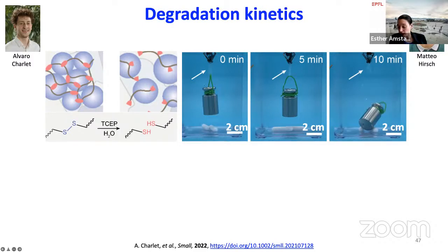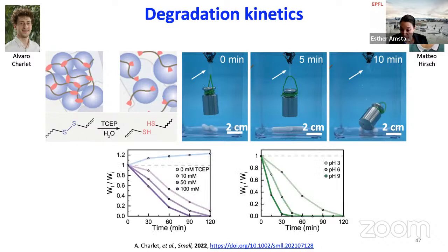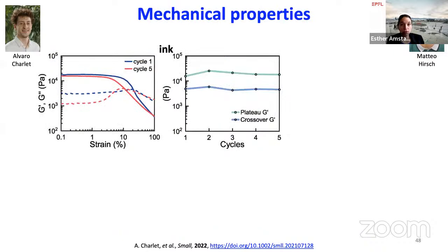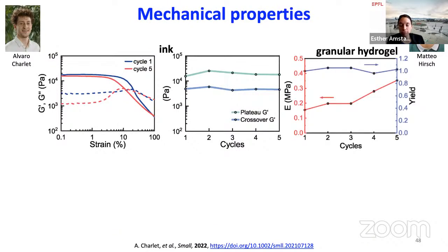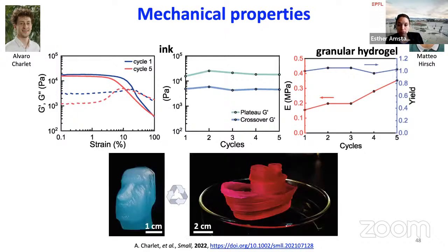And by doing so, you can actually recycle the material within a couple of minutes to hours, depending on the conditions that you choose. We showed that neither the rheological properties of the ink nor the mechanical properties of the hydrogels strongly depend on the recycling. So even if you recycle it, you don't weaken. If anything, you strengthen the material, which is one of the major limitations of the recycling of some of the most commonly used plastics that become weaker and weaker with recycling. So we really don't suffer from that. Why? Because the particles themselves remain integral. And so we could recycle these materials over and over again.